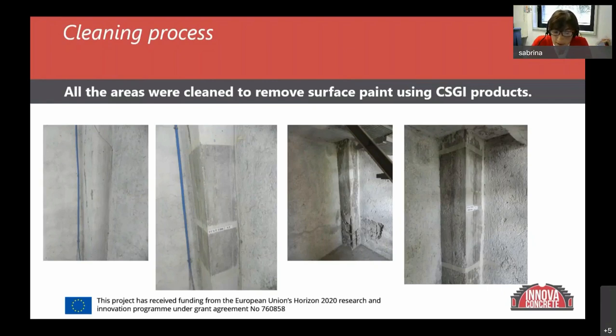To this purpose, we used the cleaning systems developed by the CSGI that permitted us to completely remove the paint without any residuals on the surface. The product was directly applied in form of compresses. In some cases, an additional mechanical intervention was necessary. The CSGI systems were compared with traditional cleaning systems to verify the efficacy, the respect of treated surfaces, and ease of application and use.